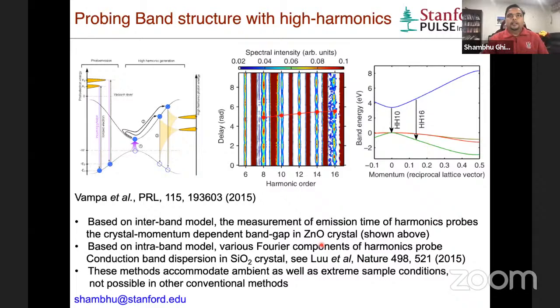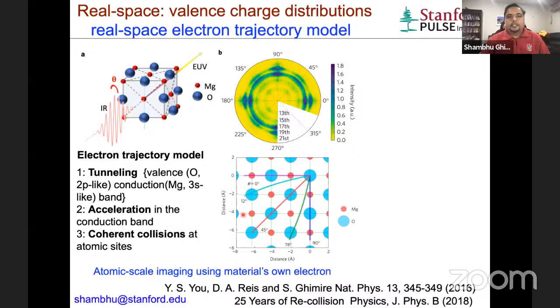Similarly, you could do the same thing in real space. Meaning not the band structure, but it's kind of similar to the nitrogen molecule example that we discussed. So this is the magnesium oxide crystal. Here, what we did is we rotated this crystal with respect to the laser field for a linearly polarized case. And you see, this is the experimental data. This is raw data. Considering a cubic crystal, which is fairly isotropic, this is a very anisotropic signal, as you can see. Kind of like the nitrogen molecule, right?